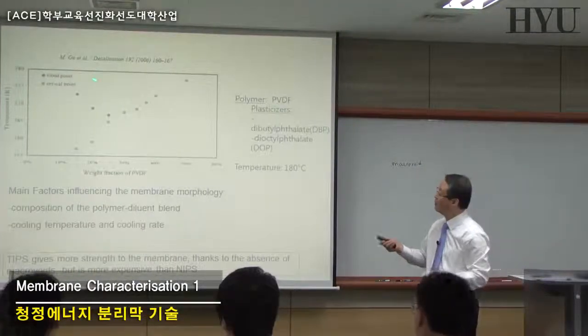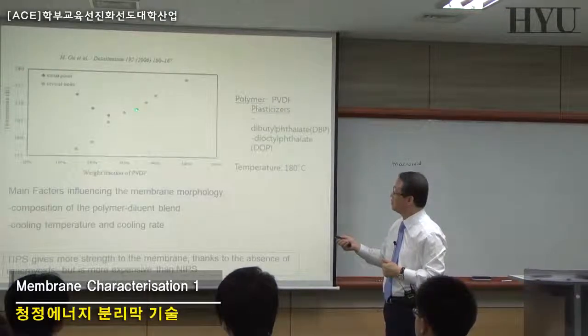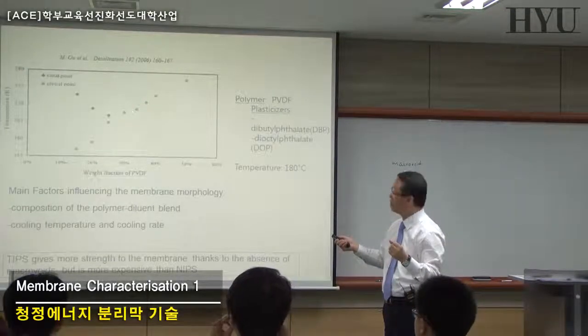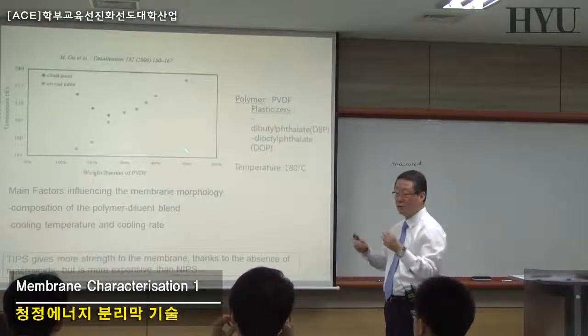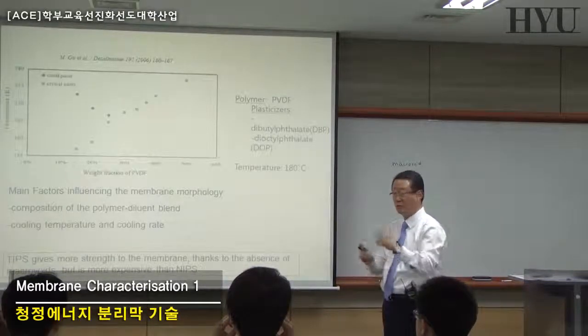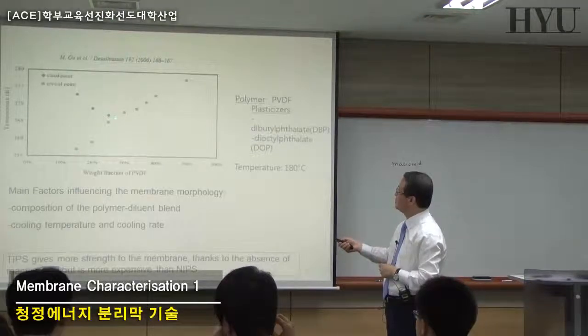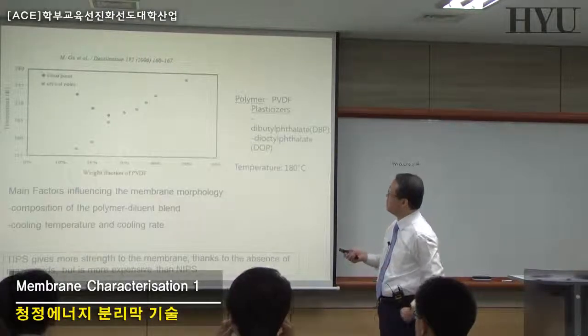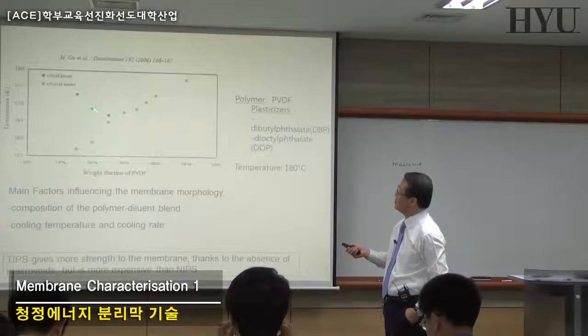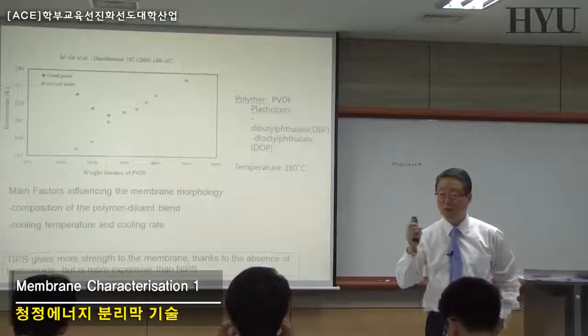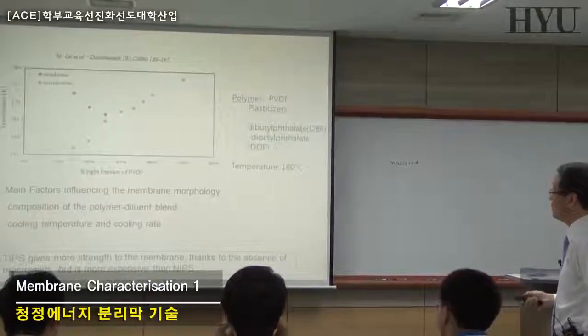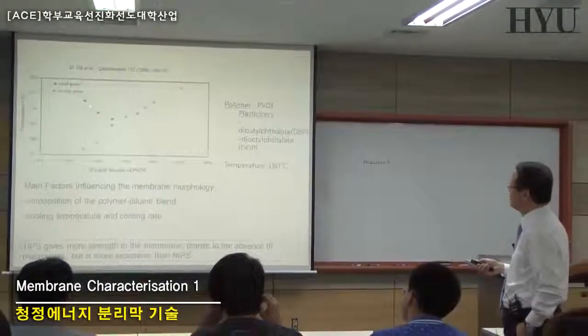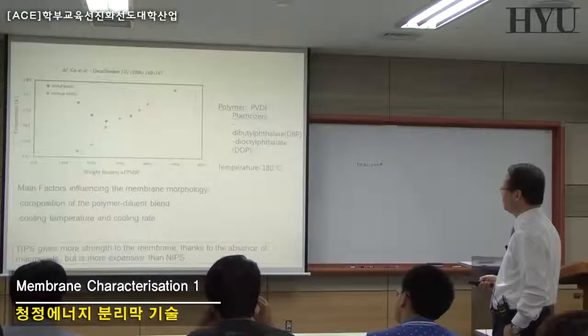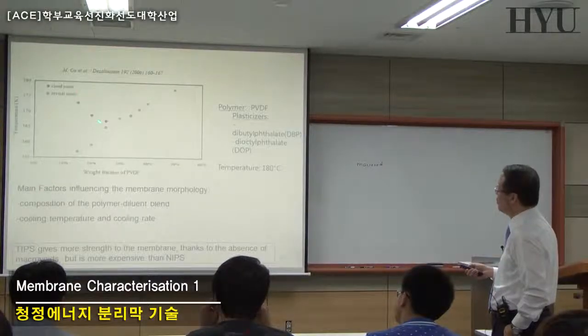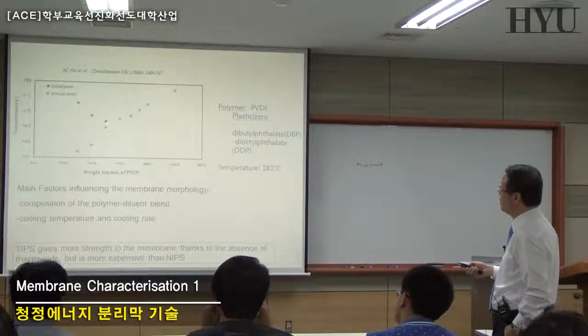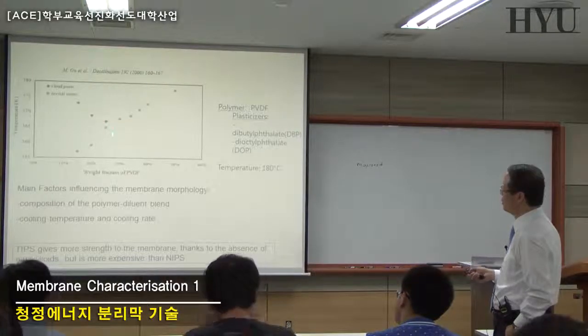Okay, and if you cool down your temperature, then you can find the crystallization temperature by changing your polymer concentrations. By adding your polymer and cooling down your temperature, you can measure these points. This is the point where you have crystals, and this is the cloud point where you form your clouds. You can precipitate your polymer by changing the temperature. So when your cloud point and crystal temperature meet, this point is called the monotectic point.